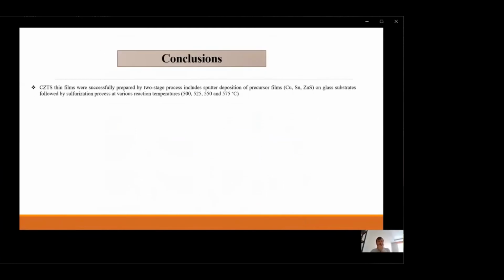Our conclusion: it can be seen that CZTS thin films were successfully prepared by a two-stage process using both stacking orders and different reaction temperatures. Most of the films have a copper-poor and zinc-rich composition, but it was seen that the reaction temperature has a significant impact on the chemical composition.